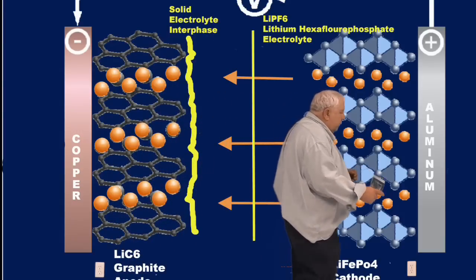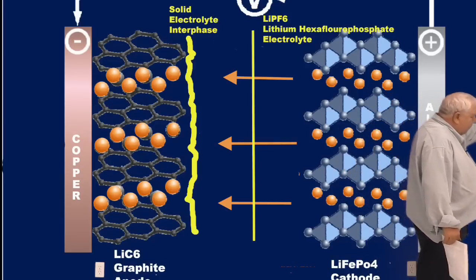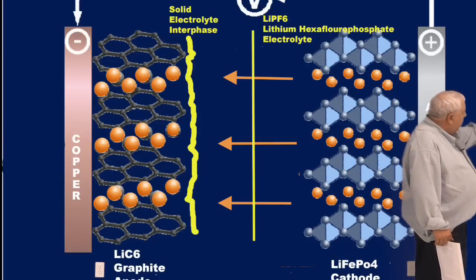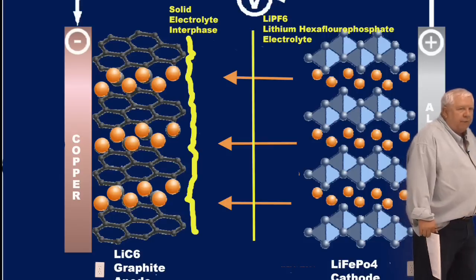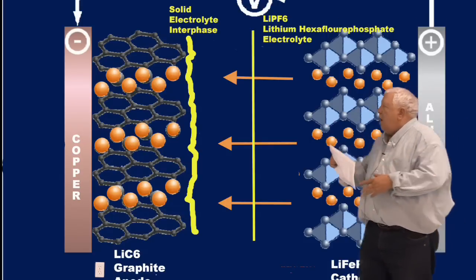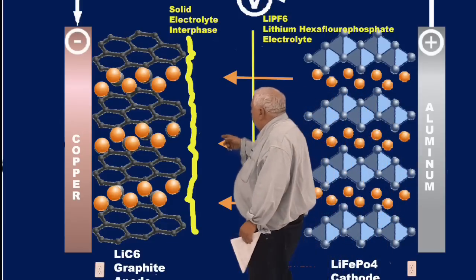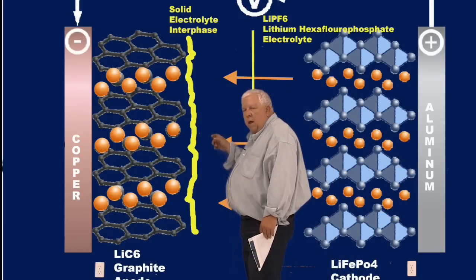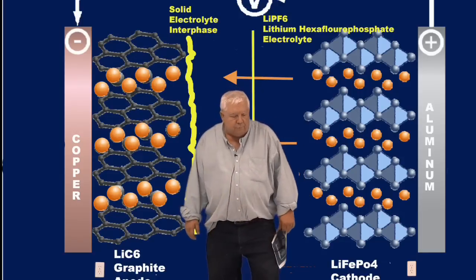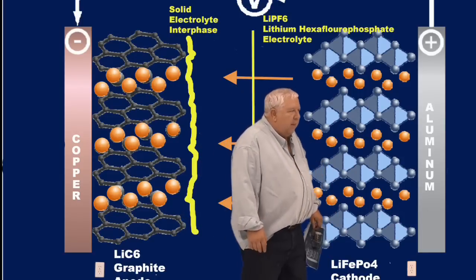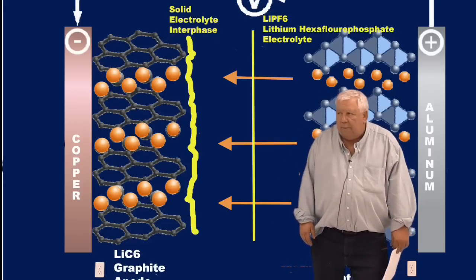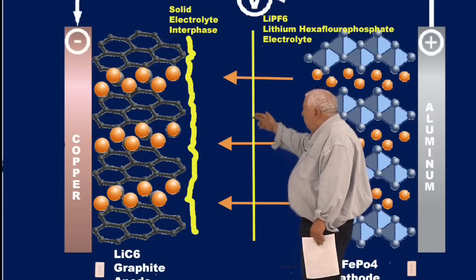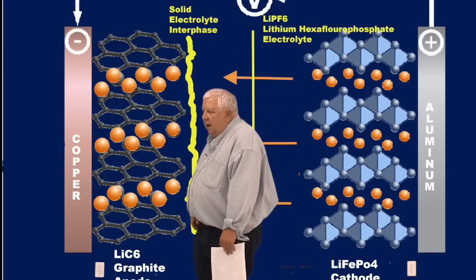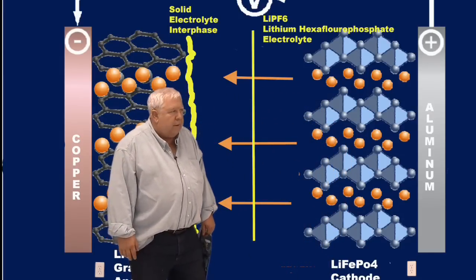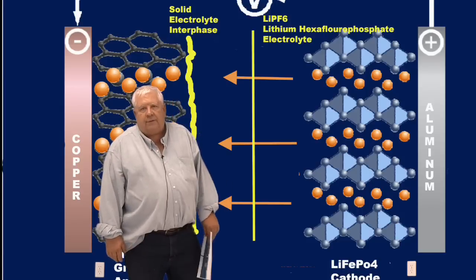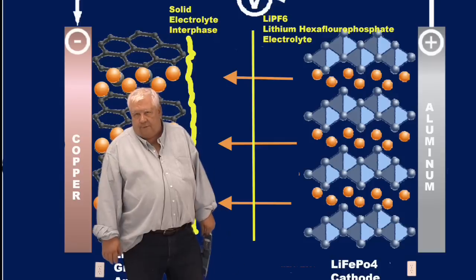It also shows up over here from certainly the iron in the thing. It builds up on the cathode side. And so we have 2 needles growing toward each other that are really only separated by a 3 mil plastic garbage bag. If they puncture it, they short the cell, and it discharges completely through there in a kind of violent display of current. Now you understand that all these foils are in parallel, and so that will also start to discharge all the other cells.